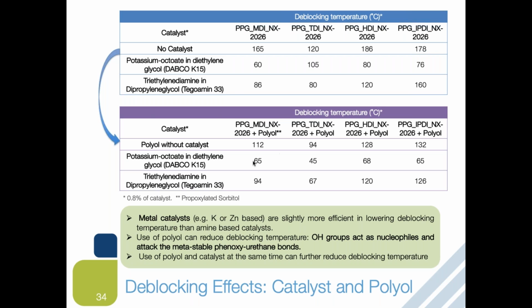As you can see, when you compare the first data to this one, by simply adding polyol, you can already see a sizable reduction in deblocking temperature. And now, polyols' OH groups act as a nucleophile and attack the metastable phenoxy polyurethane bond. That's the key mechanism to lower the deblocking temperature when you use polyols.